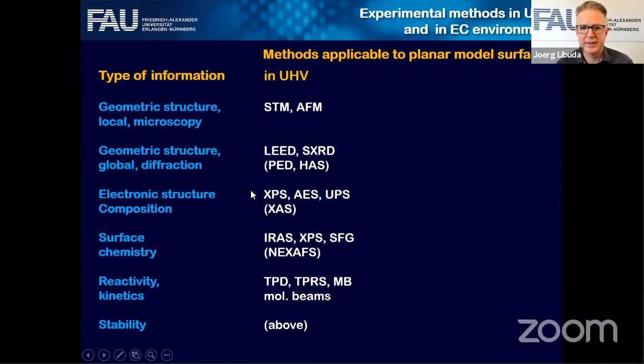For the electronic structure, people do XPS mostly, Auger electron spectroscopy, valence band spectroscopy. For the surface chemistry, you would like to do infrared spectroscopy, XPS maybe, or sum frequency generation spectroscopy. For the reactivity, you would like to do temperature programmed desorption or temperature programmed reaction. If you have a molecular beam system, you can also use that and do advanced molecular beam experiments. And for stability tests, you would use any of these techniques. So this is the UHV world, the surface science world.